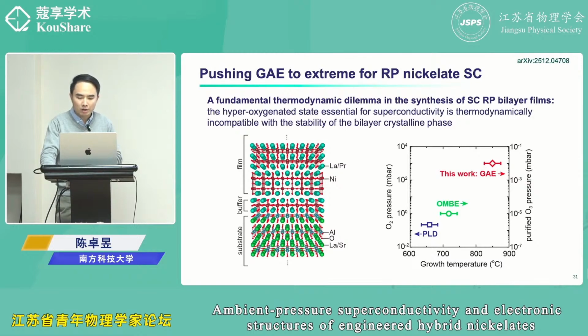And with our GAE method, we push it to an extreme. This is a highly non-equilibrium condition. It is a very, very high oxidation condition, much higher than both PLD and oxide MBE, and also a much higher growth temperature. This is 850 degrees C growth temperature. Also it is atomic layer-by-layer growth mode.